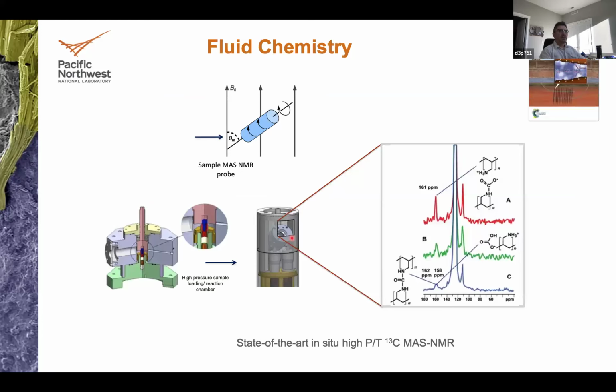So this is a speciation, basically what is the fate of CO2 and the polymer when they are both together at high pressure and temperature. And what we see here is a high pressure and high temperature magic angle spinning NMR. This is a small reactor where you can have the solution there.